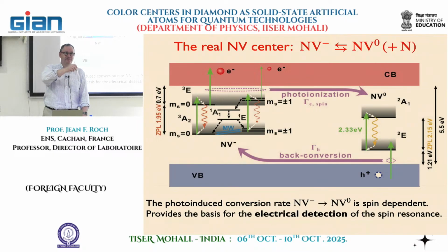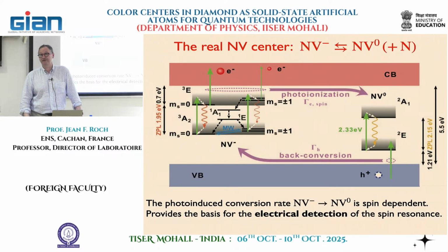So for instance, you imagine the scanning NV system, and with the scanning NV system, as soon as you have a transverse field, the T1 is very short. And the consequence of a short T1 is that the intensity of luminescence of the NV will be drastically modified, will be much lower also. So just by looking at the brightness of the emitter, you can see whether or not there is a strong transverse field.